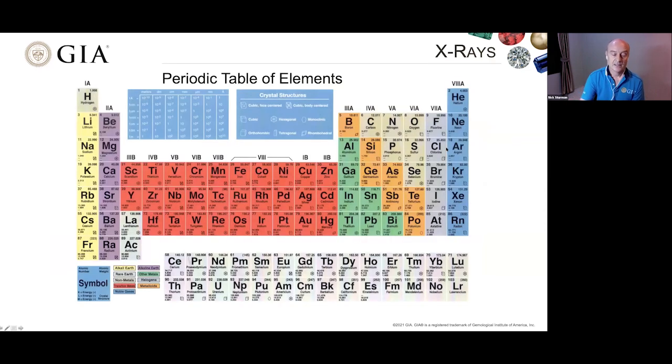It also brings me to the next important consideration when it comes to X-rays. How do X-rays and the materials being exposed interact? Generally, those that consist of chemical elements with lower atomic numbers within their composition will transmit X-rays more freely than those with higher atomic numbers. Therefore, different materials possess different X-ray densities depending on the elements they are composed of. I hope you'll see this clearly by the end of the presentation. But here is an example which will be illustrated later.